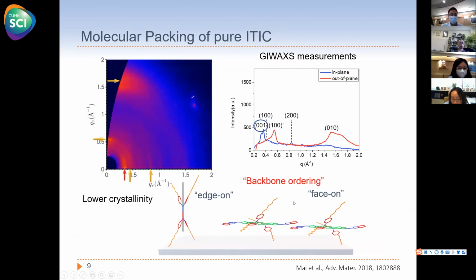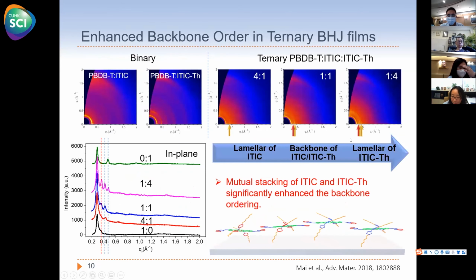Okay. Then our hypothesis is further confirmed by the scattering pattern of ITIC, which has exactly the same backbone. We can observe the backbone peak at exactly the same Q position. Although the crystallinity is lower, you can still see the first order diffraction peak, so this confirms the structural order. Then we try to enhance this structural order in the bulk heterojunction. In the binary film, we do not see the backbone peak, but in the ternary film, we can gradually tune up this backbone order by changing the mass ratio of ITIC and ITIC-TH.